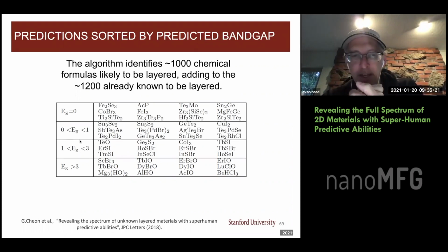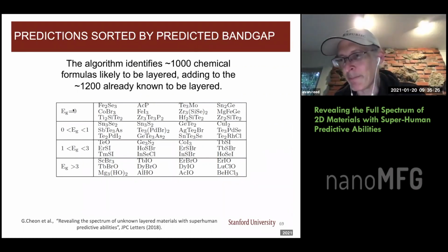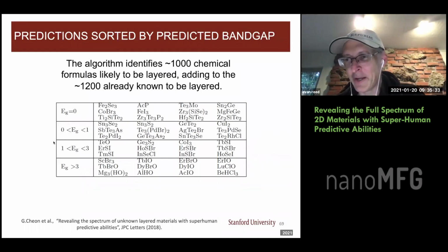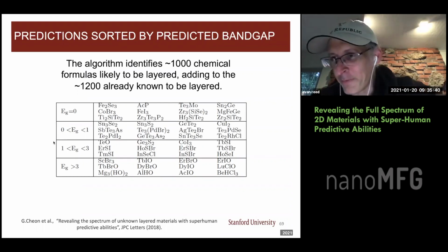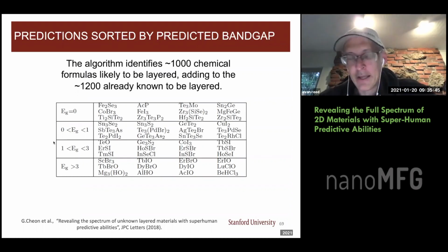The challenge is that as you get more fine grained, let's say in band gap, let's say you really want something near 1 eV, within a tenth of an eV or something, the size of your training data suddenly gets very small because there are much fewer examples of materials that have that particular property. And so the accuracy of the predictions goes down quite a bit. Oh, okay.